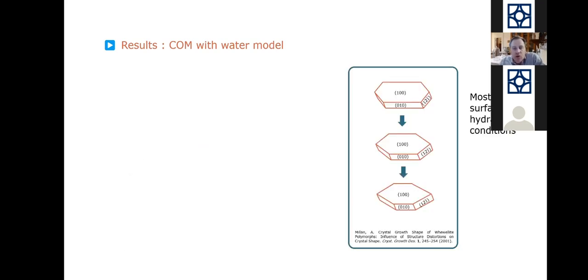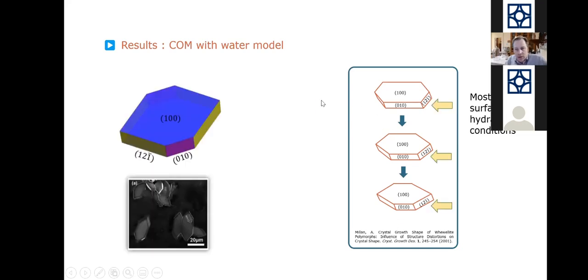And we see that with the growth of the crystals, with time, there is some competition going on. We start with a very stable one, and then the kinetics comes in again, and we see that the other surfaces start to influence it. And then we see a change in morphology with time. Okay, so this is the site here, this orientation that changes as a function of time due to the kinetic effects.